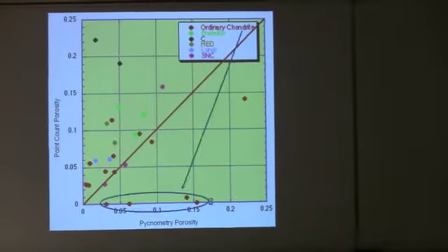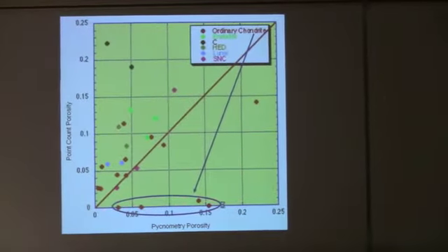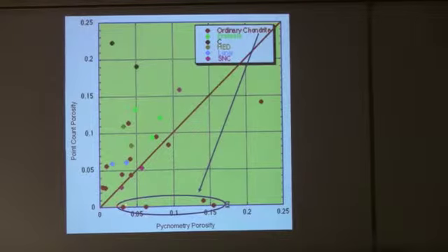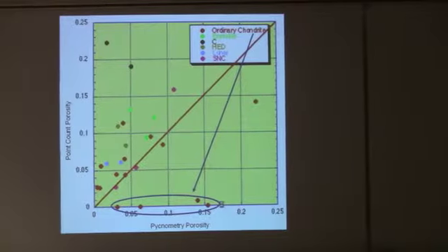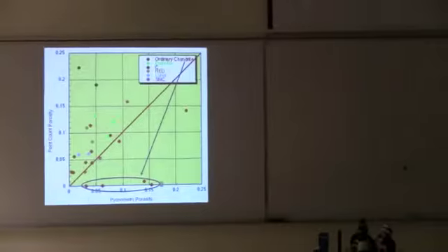So this is the early set of data comparing hand sample porosity and the point counting porosity. Most of them fall on the line. There are a few over here. When we look at them, as we expand it out into other kinds of meteorites, the ordinary chondrites still tend to agree the best, but within the ordinary chondrites, you notice there's a few down here where I'm saying they're all close to 0%, and helium pycnometry is getting anywhere from 3 up to about 15%. I thought, what the heck is going on there? Everything else agrees within the error of my correlation line between the two methods.